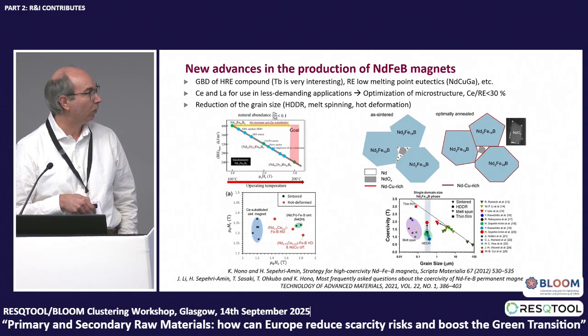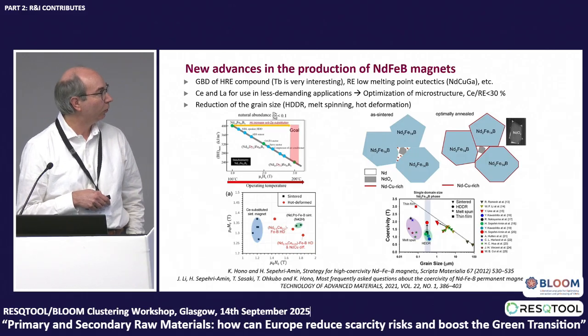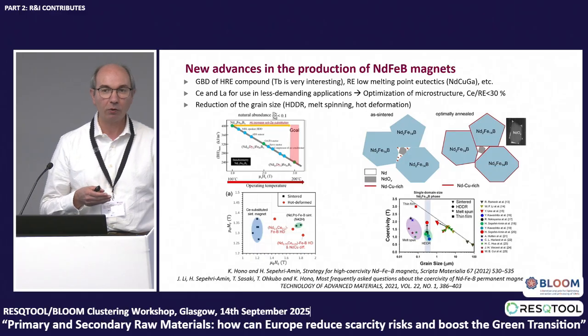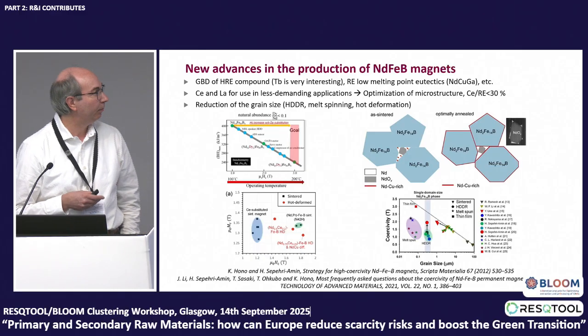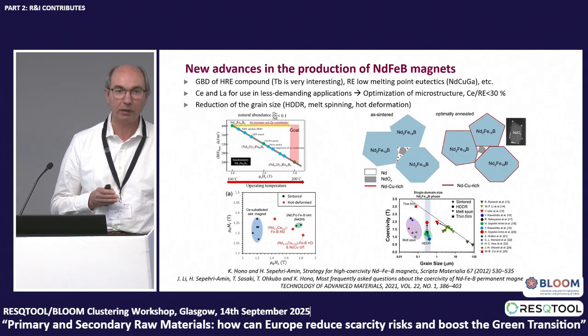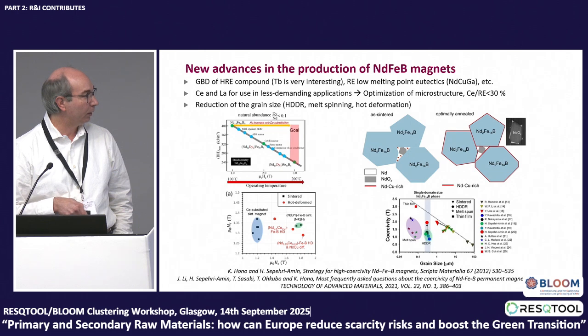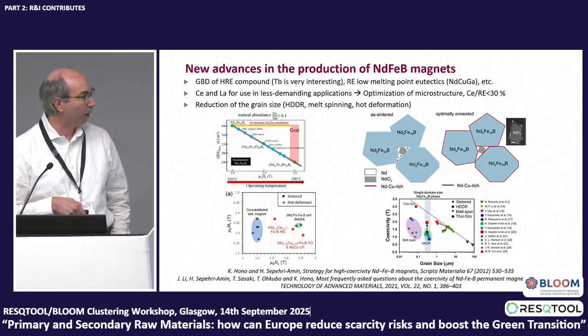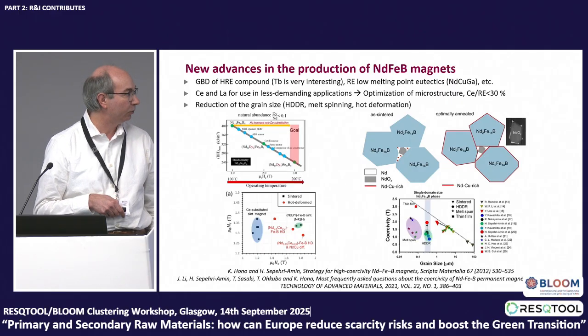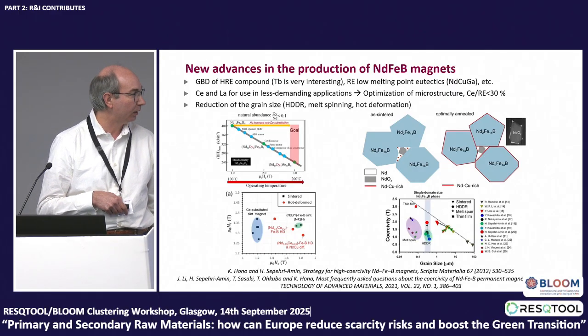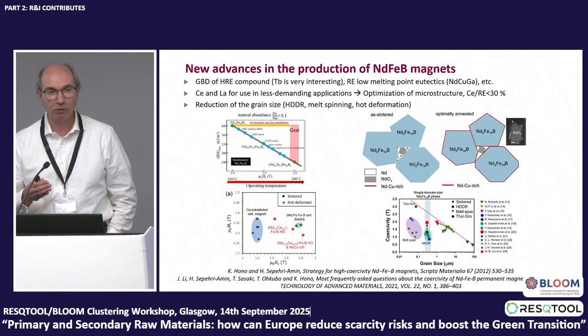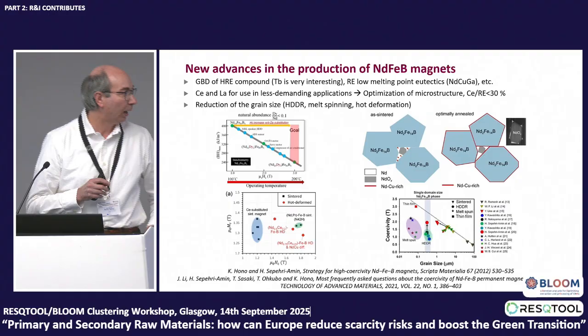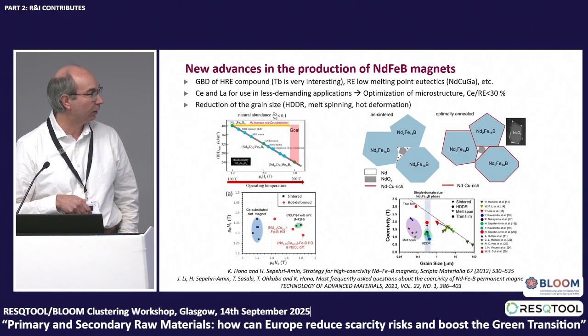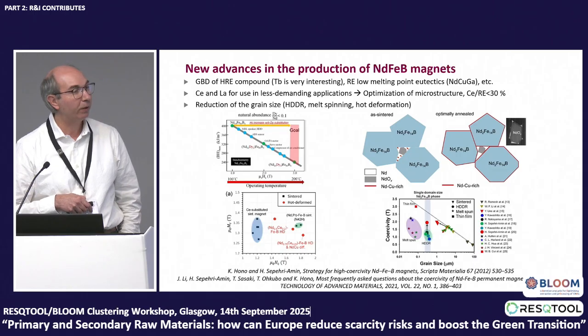The first one is to keep studying grain boundary diffusion, not only using heavy rare earth compounds, but other compounds, basically metals with low melting points that sometimes have light rare earths, but in other cases don't even have rare earths, and they improve the coercivity. The second one is to produce powders with a lower grain size using basically two methods, which are the HDDR process and melt spinning. But later during the processing, you must be able to keep this small grain. And the way in which people are working is applying consolidation technologies using hot deformation.